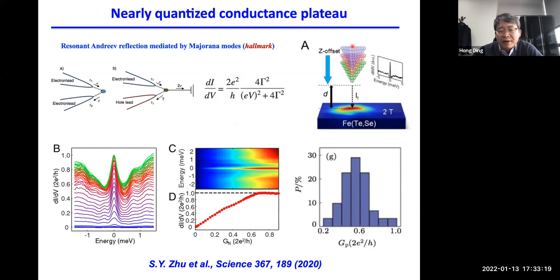We tried this experiment. We push the STM tip closer to the surface, and we see the conductance increase and reach a plateau. But reaching this 2e squared over h is very rare. In most cases, it is actually about 0.6 of it. We only have a single case out of 130 that reaches one. We think this may relate to the coupling between the tip and the surface, or you can think that the tip potential may affect the surface potential. So this introduces an additional problem and may reduce this plateau.